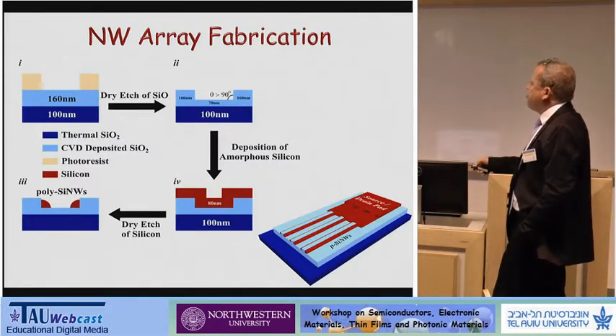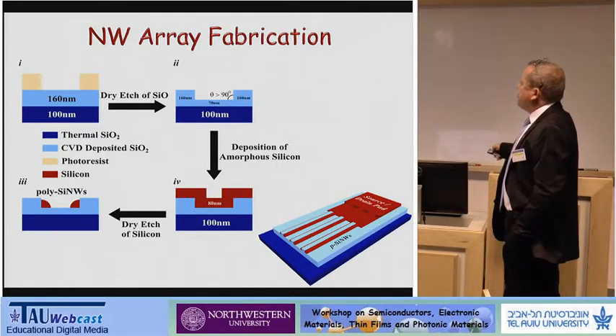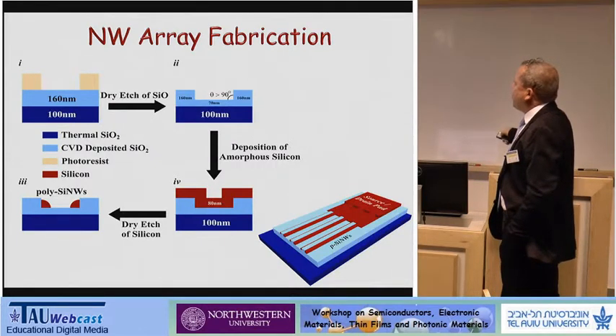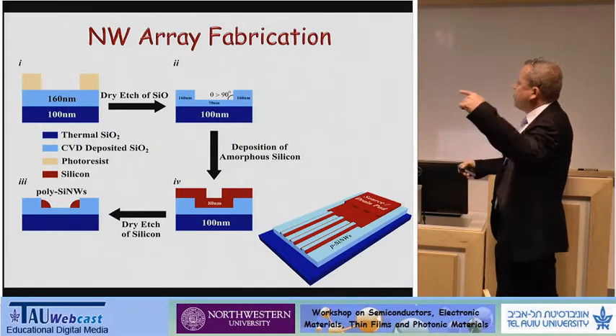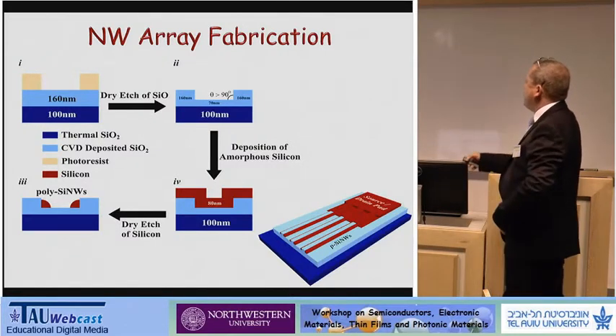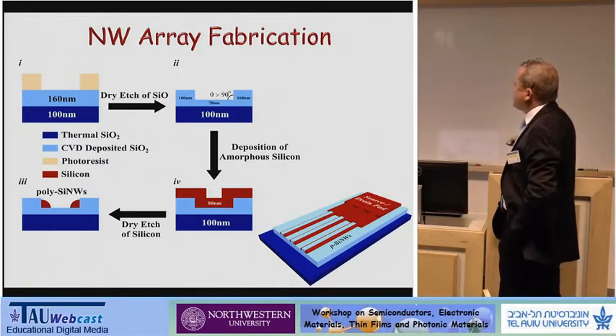So the idea is to deposit amorphous silicon. I will not go over all the steps. By etching it in a careful way, you can form these nanowires that go vertically into the board, and you can very easily have arrays of nanowires.